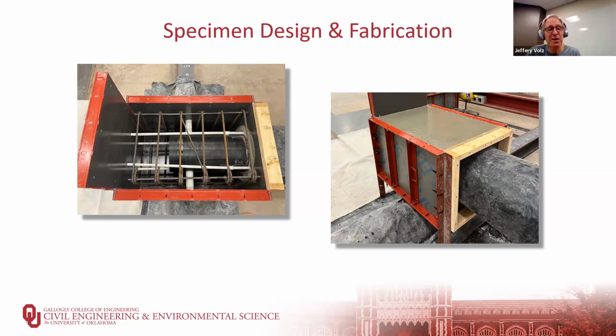And here you see one of the loading stubs before the concrete has been placed on the left. You see the steel tube extending 2 feet into that loading stub. And then you see the finished concrete loading stub on the right. And the black is just plastic to protect the existing column and the loading beam.